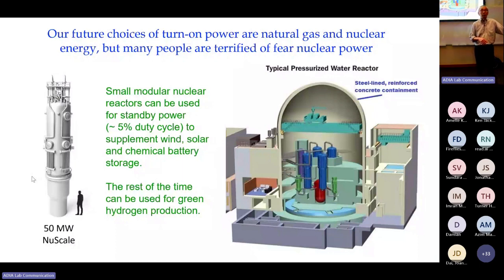If these things work, that would be very important because they can be designed to be virtually contamination proof. They have enough heat capacity that they will never melt down. So you can imagine putting these in islands where you normally wouldn't think of having a nuclear reactor because of contamination issues. Companies are also beginning to think of them at an oil refinery, behind the fence within their own site. Having a couple hundred megawatts is a good deal. Data centers would love these because that's the same scale. A couple hundred megawatts is a typical data center.